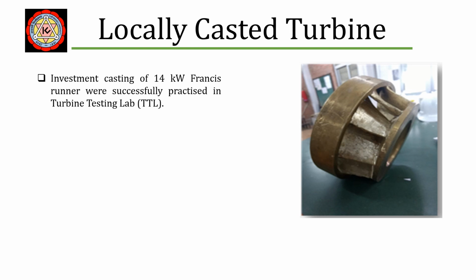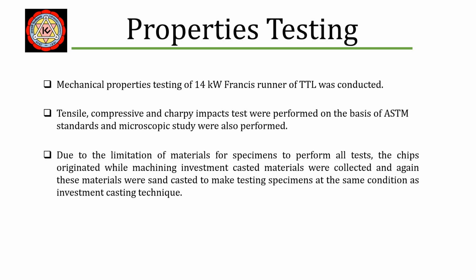With these motivations, Turbine Testing Lab has done casting of a 14 kilowatt brass Francis turbine by the investment casting method. So, to conduct our testing of mechanical properties of the cast brass Francis turbine, the runner and riser part of the 14 kilowatt Francis runner were collected, and tensile, compressive, Charpy impact testing and microscopic study were performed. Due to limitation of material for specimens to perform all tests, the chips originated while machining investment casting materials were collected, and again these materials were sand casted to make testing specimens at the same condition as the investment casting technique.